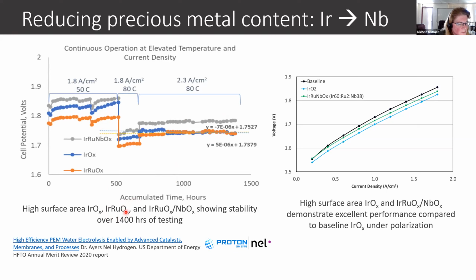I also wanted to mention that because iridium is a very, very precious metal, and it's more rare than platinum, we're also looking at opportunities to be able to thrift iridium, which means being able to use less of it per square centimeter of a device. And there we can incorporate other types of materials such as ruthenium or niobium. And these have very additive impacts, not just reducing the amount of iridium, but they also interact very favorably with